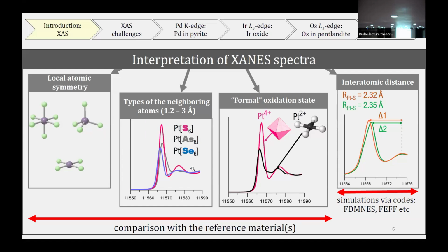Here is an example for platinum. And of course, we can define the formal oxidation state, which might be different from the real one, but from the idea that our bonding is purely ionic, we can define the formal oxidation state. Yeah, and also we can apply different ab initio methods like FDMNES and FEFF and simulate these spectra, having the XYZ coordinates, and compare them to the experimental ones, which sometimes can be helpful in interpreting the experimental results.